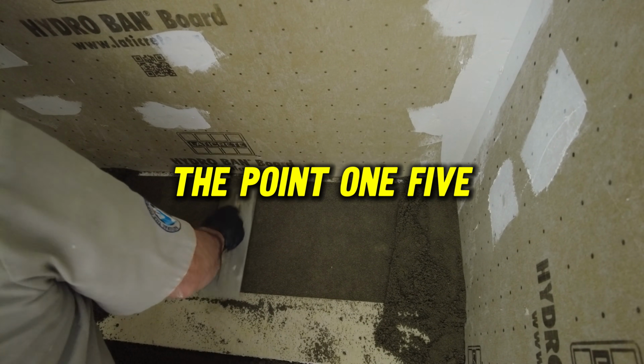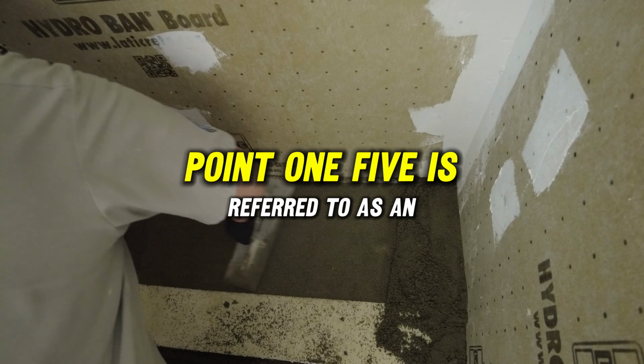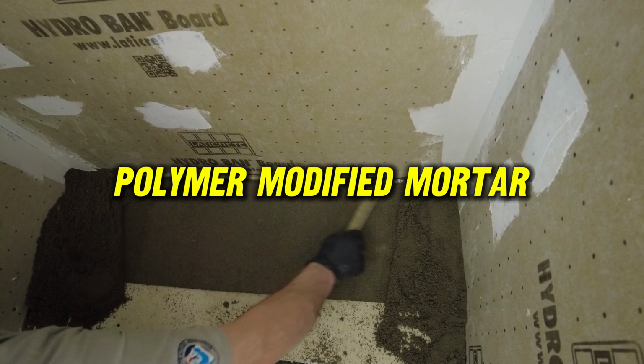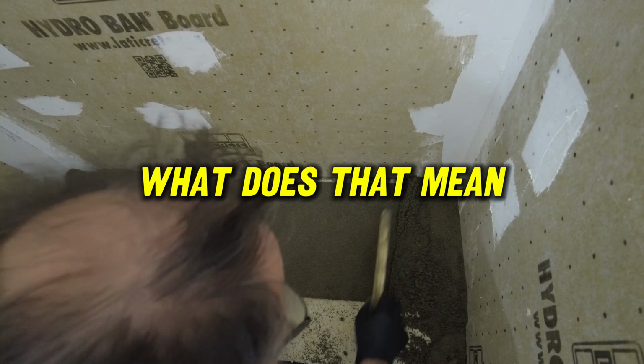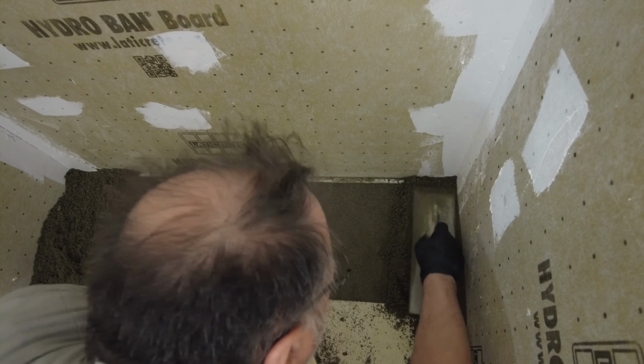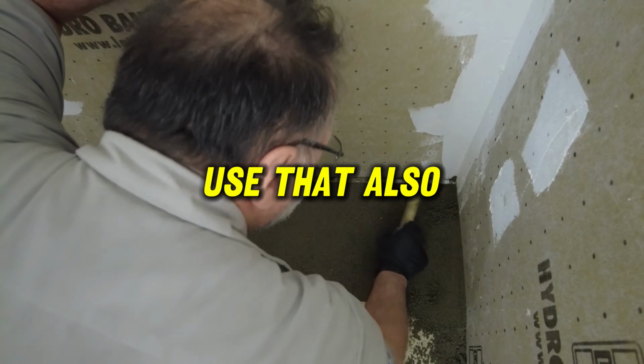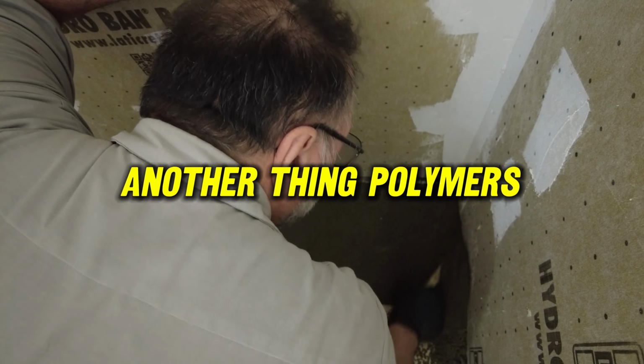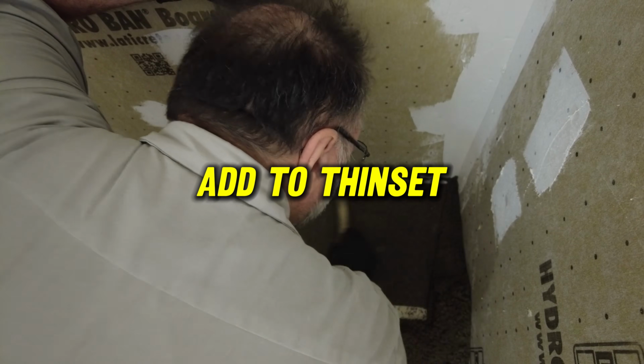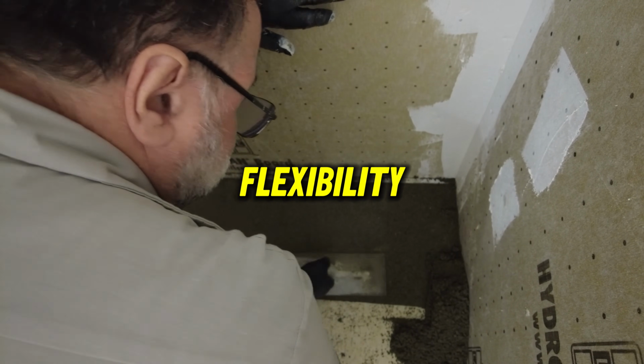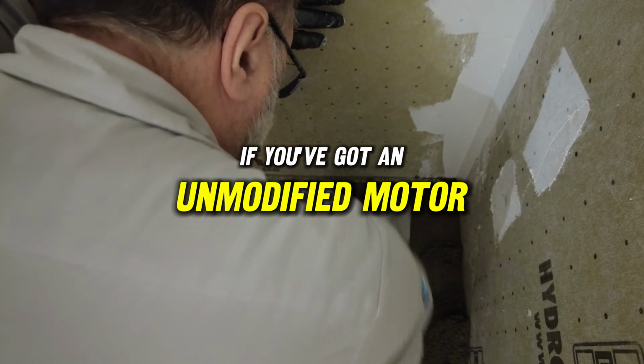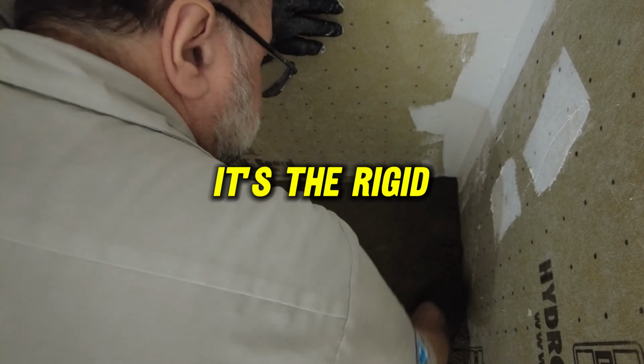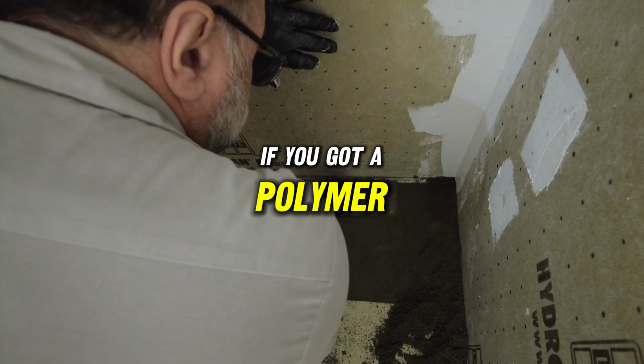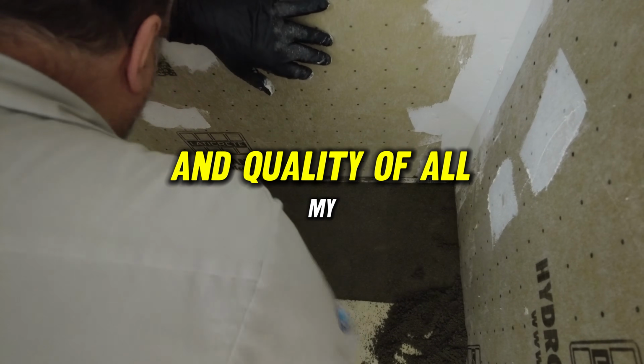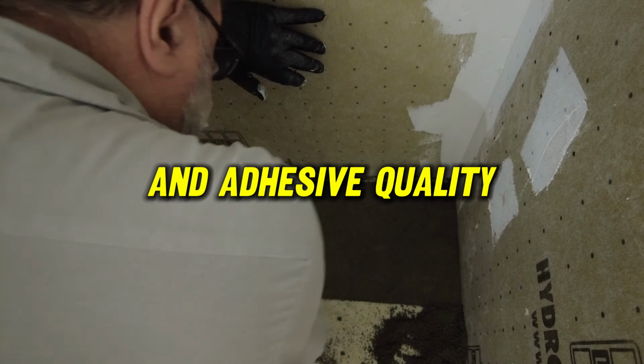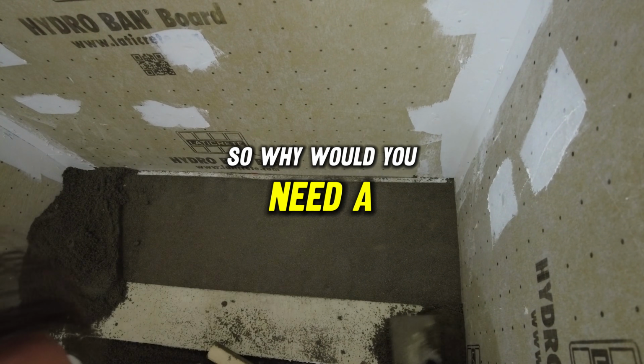And then you got the 0.15. The 0.15 is referred to as an improved polymer modified mortar. What does that mean? Improved, it's better. So you could use that also over plywood. Another thing polymers add to Thinset, it gives it flexibility. If you've got an unmodified mortar, there is no flexibility. It's just a rigid material. If you've got a polymer, and depending on the type and kind and quantity of polymer, it adds flexibility and adhesive quality.